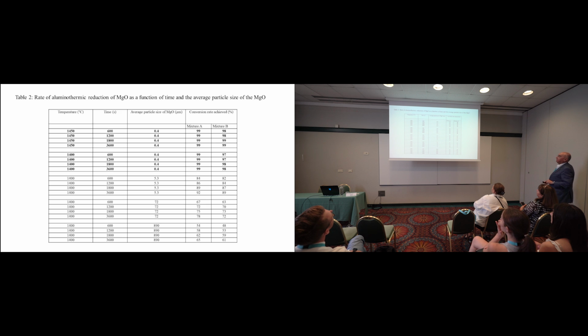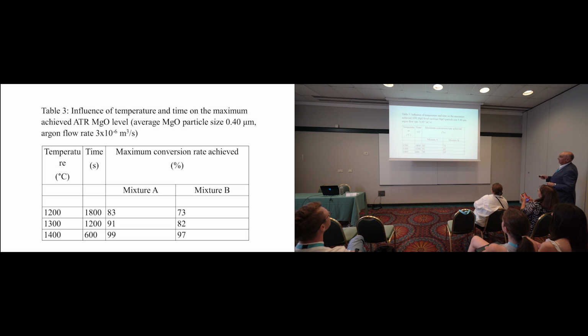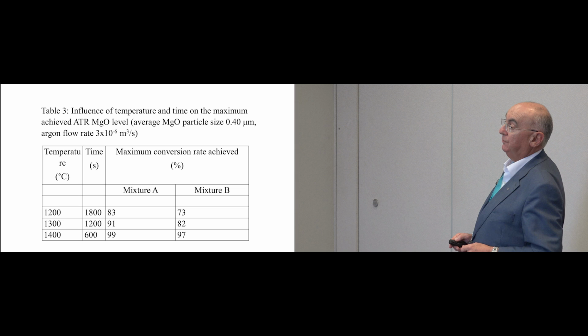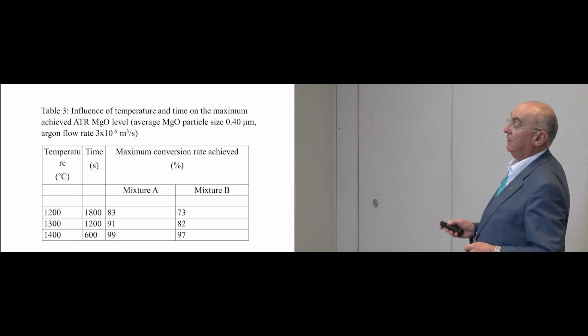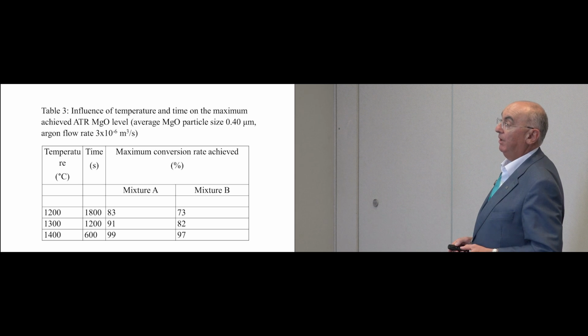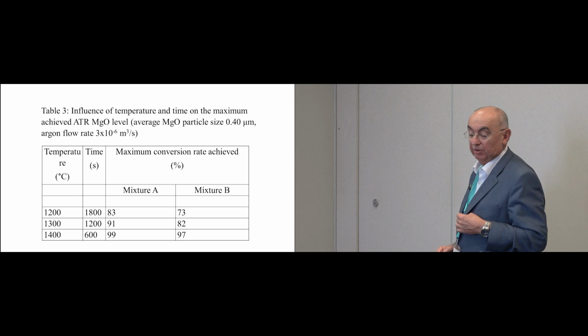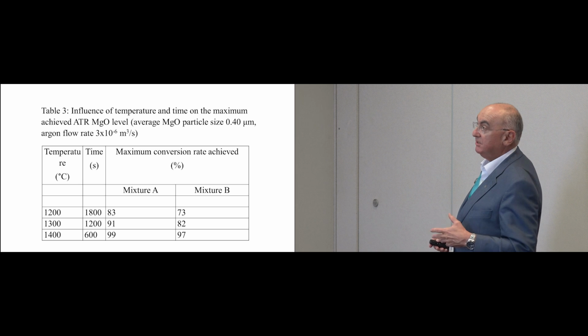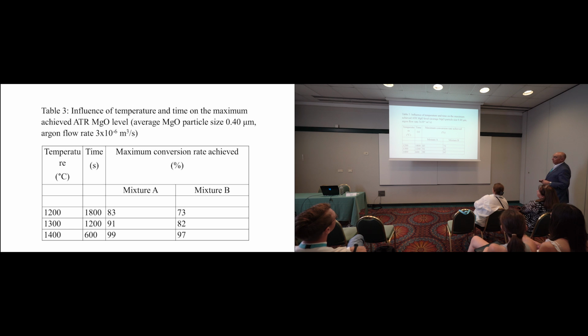A lot of work, but in principle, we investigate two mixtures, as I said, at some different temperatures, between 1,200 and 1,400, for different time, 10 minutes or 1 hour. And what we found is here. And this was one of the key results for us. We found that at 1,400 degrees, in 10 minutes, you can achieve very high reaction yield. But, of course, only if you use magnesium oxide particles in submicron range. So, in 10 minutes, it's very fast and fast enough for continuous production.